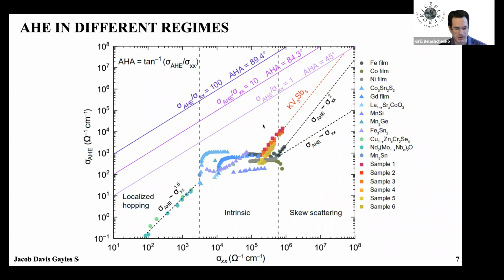So in this case, it's natural to question whether it's the Berry curvature that generates this effect. The anomalous Hall effect, you mean? Well, in that case, it's the spin Hall, but it's the same kind of argument. Yeah, I'm not sure. I mean, there is no anomalous Hall effect in platinum, but the same question about the relation between the gaps that generate the Berry curvature and the contributions to these intrinsic effects and the scale of the disorder broadening. So it doesn't seem like disorder broadening is much smaller than those gaps.